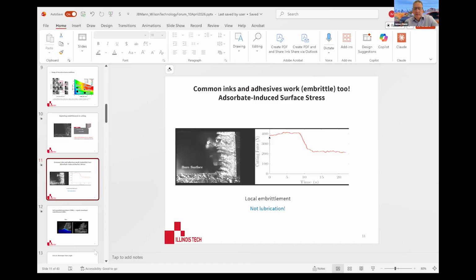induced effects. In this case, surface stress that is on the surface of the workpiece. And this is an example where these so common inks and adhesives, benign media, can actually be used to embrittle the material. And so on the left is another example of cutting, and on the right is tracing the force in cutting, and it's bare, and then it hits a surface that has a thin layer of, in this case, an ink or glue, a thin layer of media.